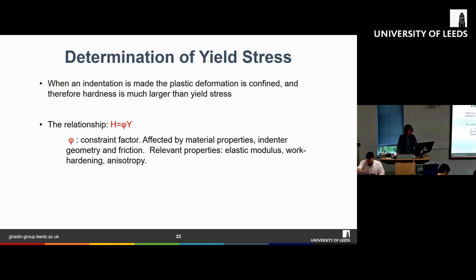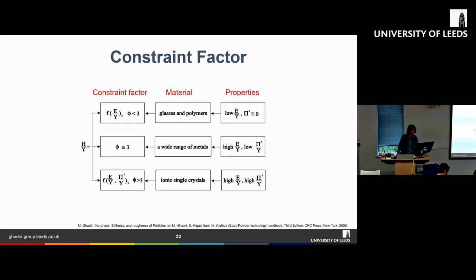And this constraint factor is affected by material properties, the indenter geometry, and also the friction. Some of the relevant properties are the elastic modulus, work hardening, and anisotropy. These are the constraint factors of some common materials. For glasses and polymers, we are talking about constraint factors of less than 3. For a wide range of metals, it's more or less around 3. And for ionic single crystals, we are talking about constraint factors of higher than 3.